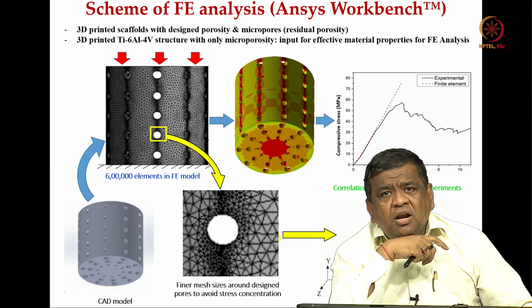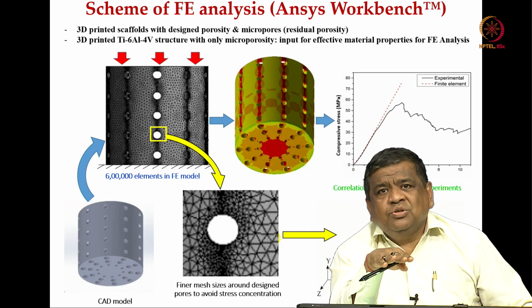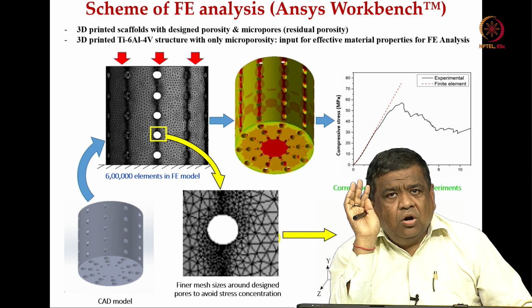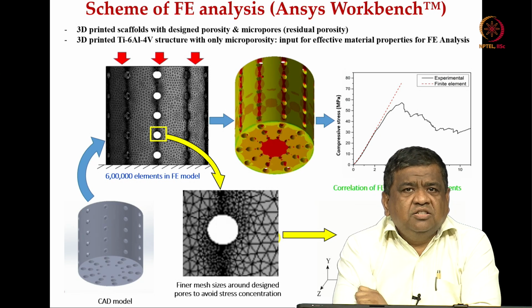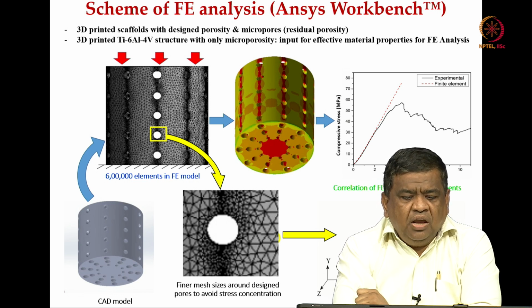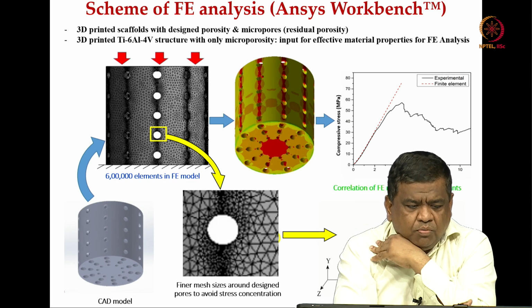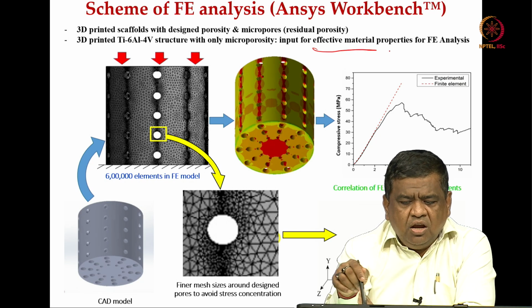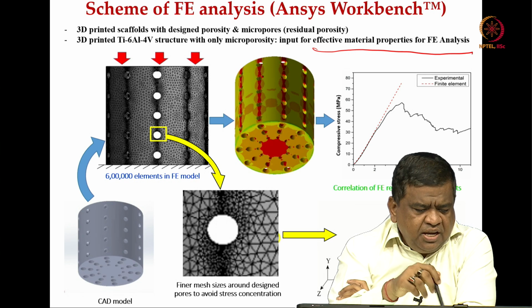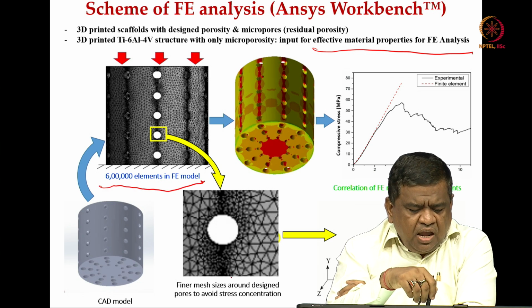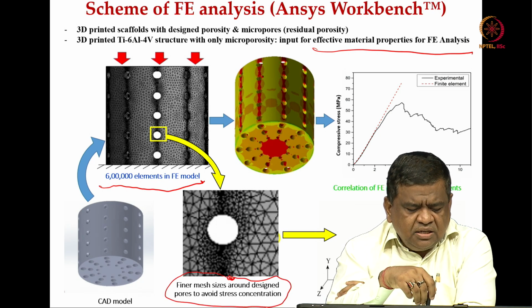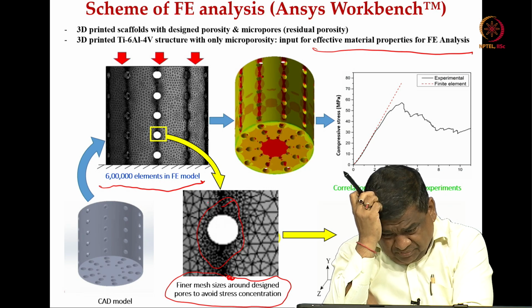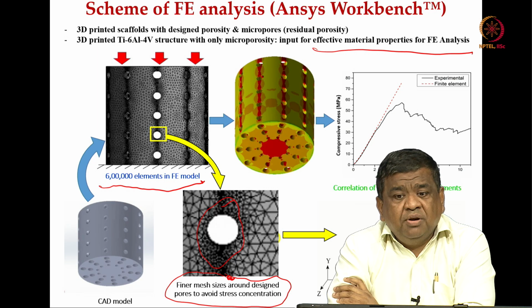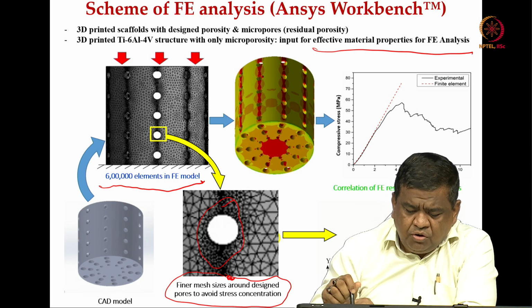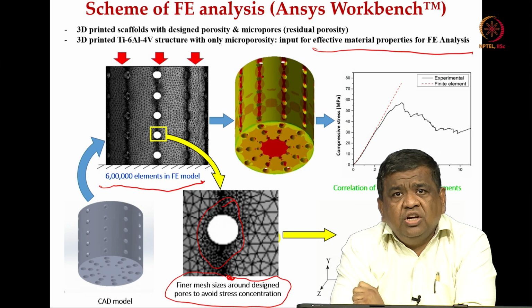So, it is important to understand that after microCT, whatever 3D reconstructed image you get for the entire cylindrical structure, it is better to use that as an input to the finite element analysis. Okay. So, 3D printed scaffolds with designed porosity and micropores, and this structure with porosity, serve as input for effective material properties for finite element analysis. What you see here is 600,000 elements in the finite element model. From finite element analysis, you know that the finer the mesh size around the pores, the better the approximated material properties you get. The mesh is 10 noded tetrahedral elements that we used in the finite element analysis.